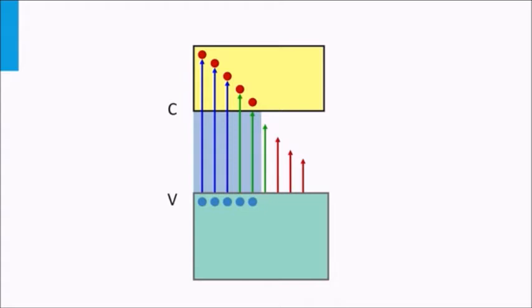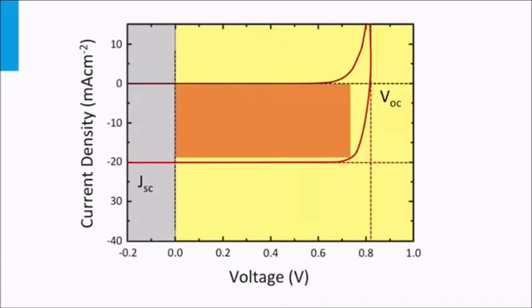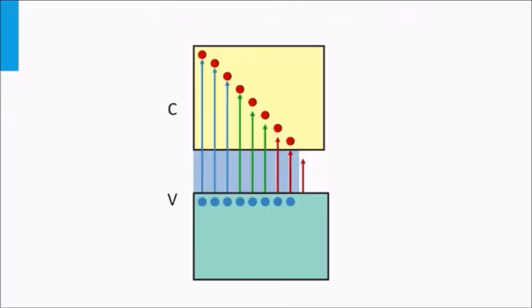Note that in this illustration the band gap is relatively large. Only the blue and partly the green photons are able to excite charge carriers. If we look to the JV curve, this is indicated by a relatively low short-circuit current density, while due to the large band gap, a higher open circuit voltage can be obtained.